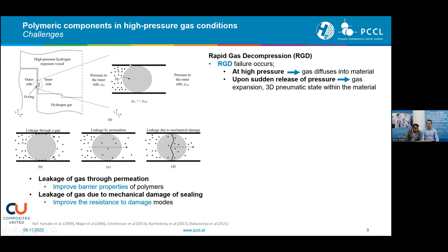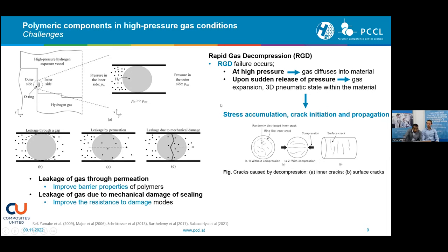How does it happen? It happens when, for example, the sealing is exposed to the high pressure gas, then this gas goes in, and if the outer pressure is suddenly released, then this gas tries to go out at one end, and also the gas inside tries to expand itself. So there are a lot of stresses taking place inside the material, so that we have also a 3D pneumatic state within the material. If these stress levels are high enough, they initiate cracks, and if they are even higher, then they could even propagate to the outer surface. So here you see an example of how these cracks could be inside.